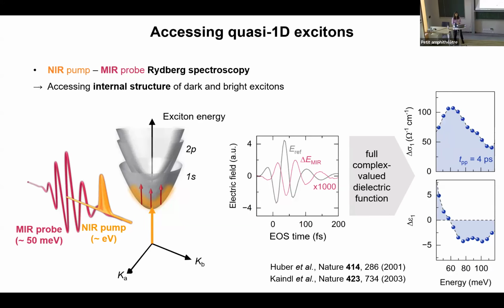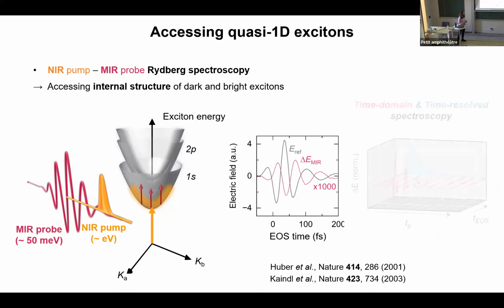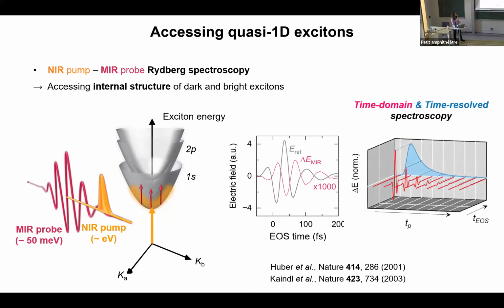We can even go a further step and develop our measurements to a next level. How we do it is that we start recording these transmitted mid-infrared pulses as a function of the delay between the near-infrared and mid-infrared pulses, and we trace how its amplitude changes over time. And this gives us the ultrafast formation and relaxation of excitons across time, right?